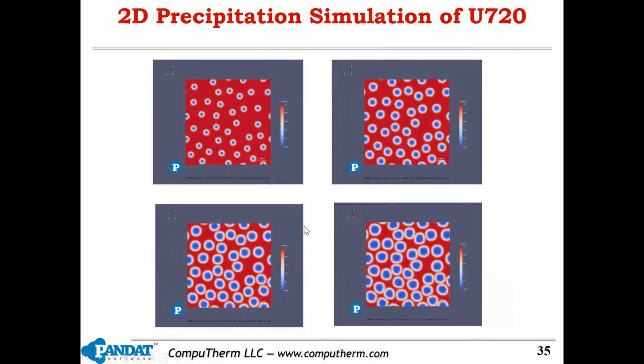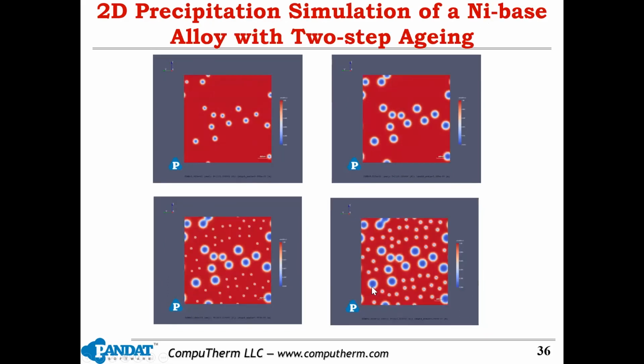This one, and also, as I said, the purpose is to use this module for industry applications, right? So we can apply it to multi-component systems. In this case, we apply it to nickel-based superalloy U720, which is a multi-component system. Again, as you can see, the particles nucleate, grow, and coarsen, and so on. And also it's not limited to isothermal aging. We can consider a 2-step aging, for example, and you can see in the first aging step, you have nucleation and growth. And then when you drop the temperature, some new nuclei will form and grow. So you can see clearly the secondary and the tertiary gamma prime, okay?